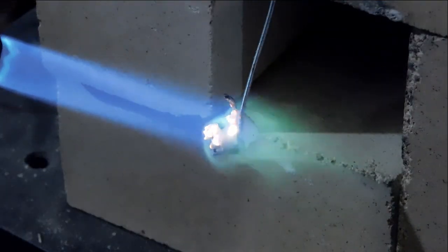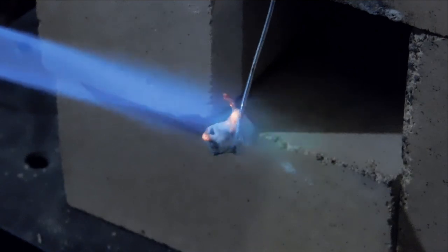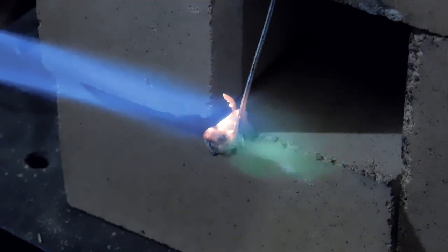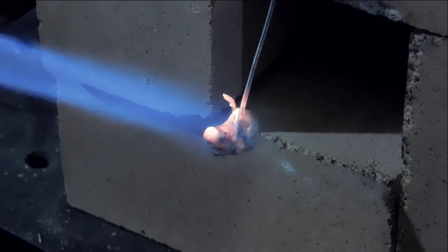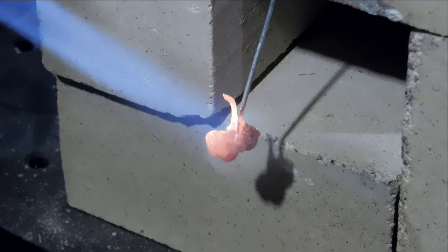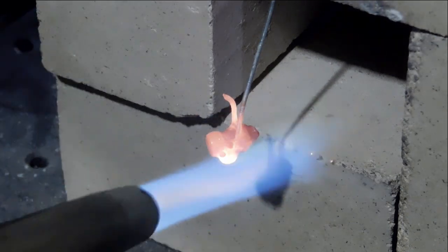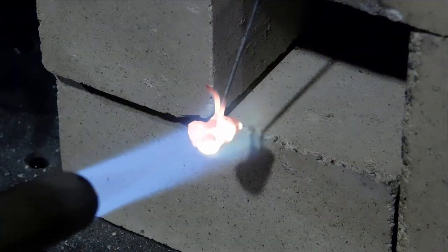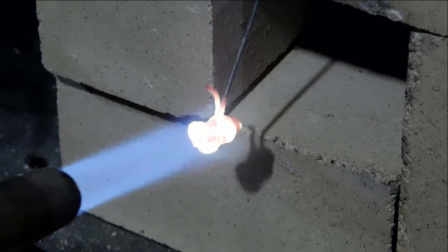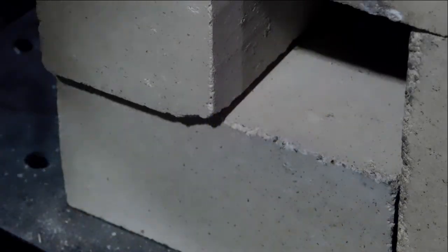Okay, I've covered it with boric acid and alcohol, and I'm using MAP gas here to heat it up. I only have a single turn around on that wire holding it—it hardens better for me when I do it this way. So now we're just waiting for it to turn cherry red, and then I've got a little glass of water off to the side and I'll quench it in that water. You can see how well that boric acid and alcohol does to keep the scale from forming on the screw itself. It's getting up there now, starting to turn red, there we go, that's looking pretty good. Alright, let's take it over and quench it.